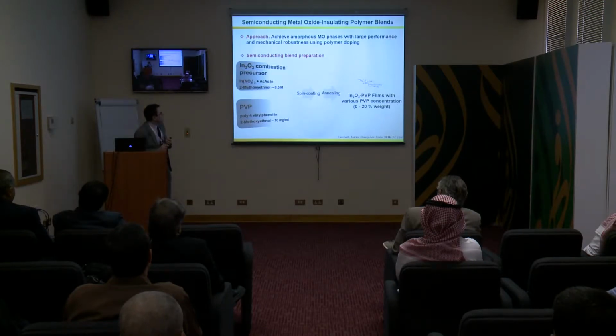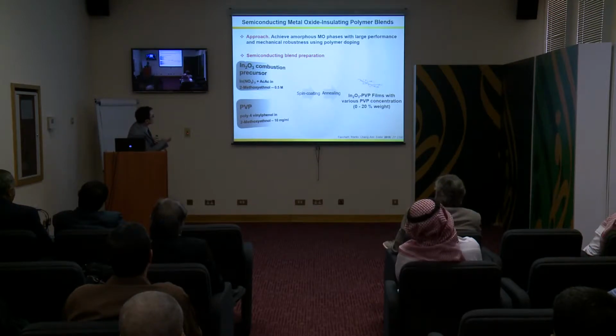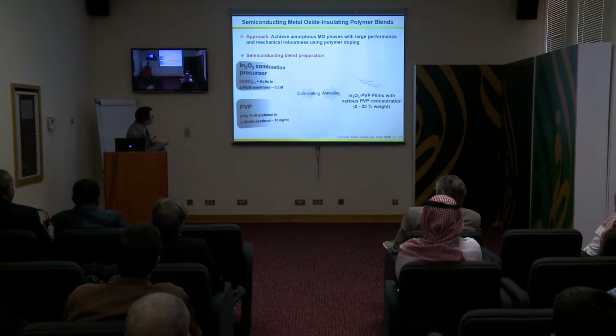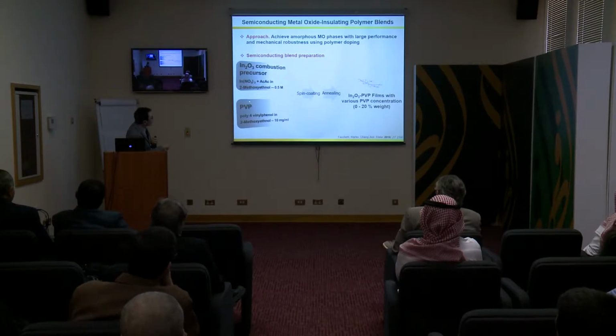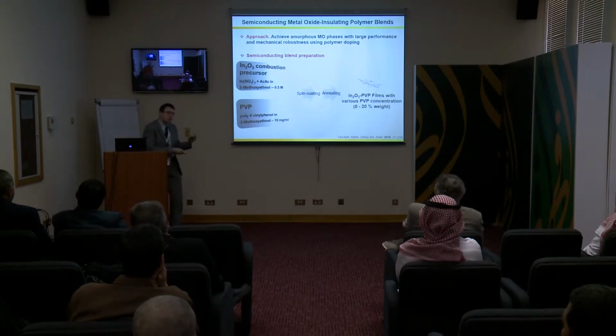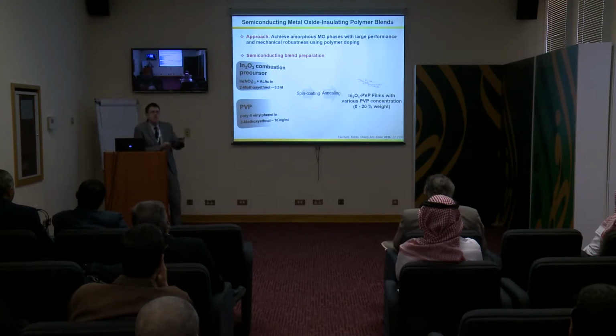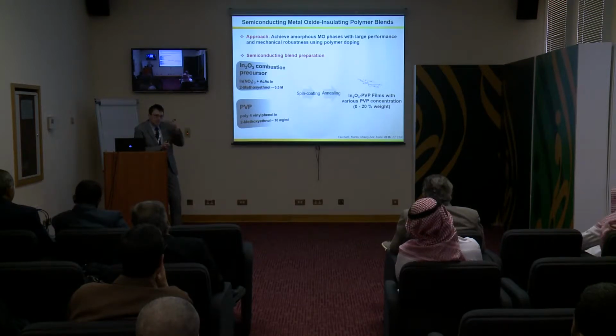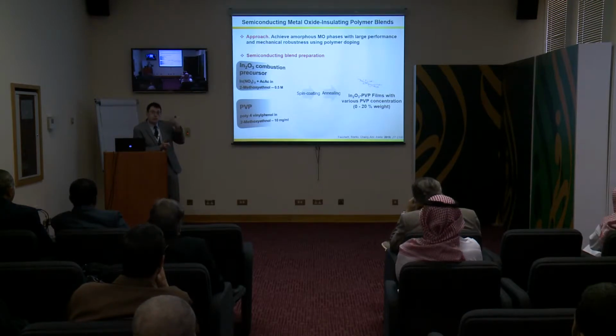A new way, which was recently discovered, is actually to take your matrix, which is in this particular case indium oxide, and then we use an insulating polymer, which is soluble into the metal oxide. And we are doping this matrix with an insulating polymer. So the question is, can this metal polymer be creating amorphous phase? What is the microstructure of the film? What is the charge transport capability? How do they change? So there is a few questions we had to answer.